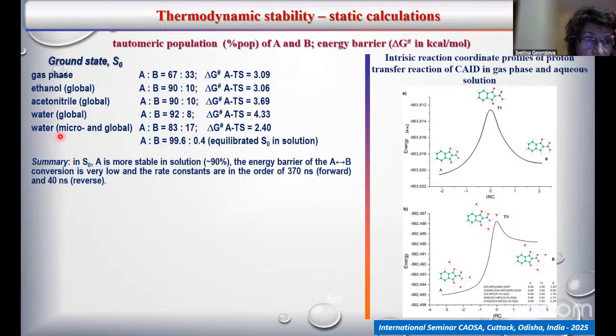Solution, global and micro and global models. The picture slightly changed. The relative energy between A and B is larger, and the population also changes. In summary, in ground state, the A form tautomer is more stable in solution, about 90%. The energy barrier of conversion is very low. You can see this value, and the rate constants are in the order of 370 nanoseconds for forward and 40 nanoseconds for the reverse reaction.